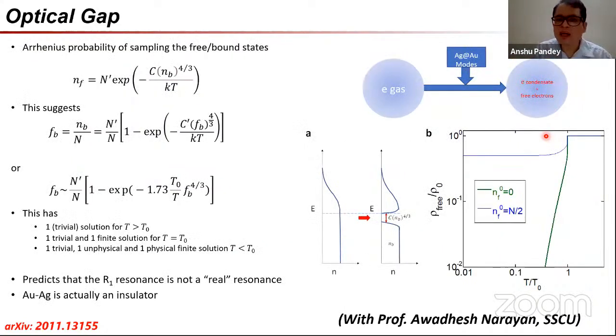If we assume a simple probability of free and bound states, in that event the number of free electrons is given by this exponential factor, and this can be rephrased into the following term, where the fraction of bound electrons in the material, FB, is ultimately a function of itself. And this equation is particularly nice because of this factor of 1.73. So it means it's a mean field model for this localization.